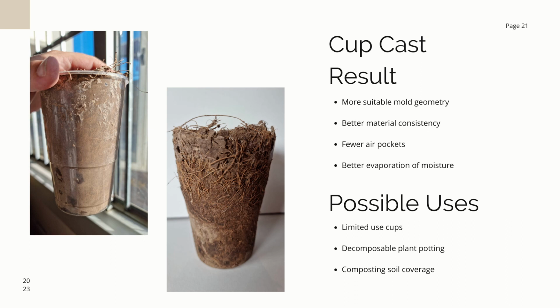The material consistency was much better as well. Wall thickness around the whole cup was all quite equal to each other. There were no thin walls or too thick walls, so it was all very consistent. There were fewer air pockets. There were tiny air pockets, but nothing to overall impact the structural integrity of the cup itself. And as well, better evaporation of moisture, so our bioresin cured much faster and actually cured compared to the first casting. So all in all, this was a much more effective method.